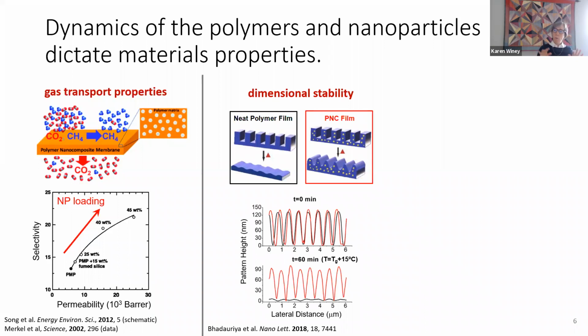Nanocomposites are also being formed. Karen, can you just speak to that a little bit? Are you making voids around the particles and it's going through the voids? What's going on there? Yeah, so the chain packing is not as efficient up against a hard surface. So there's a little bit extra free volume. And again, it's very sensitive to that particle polymer interface. So if it's strongly adsorbing, less free volume. Chain rigidity, that matters too.